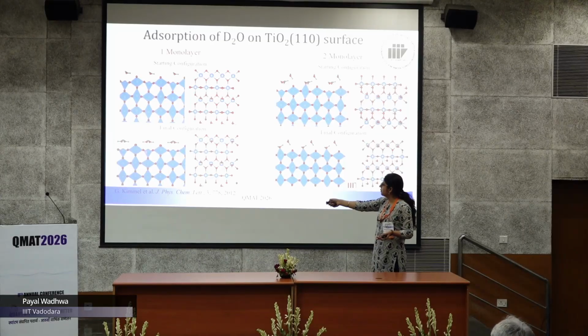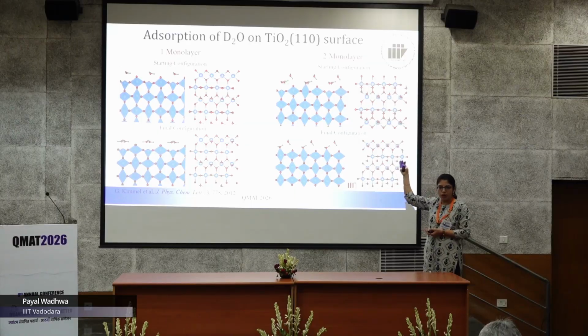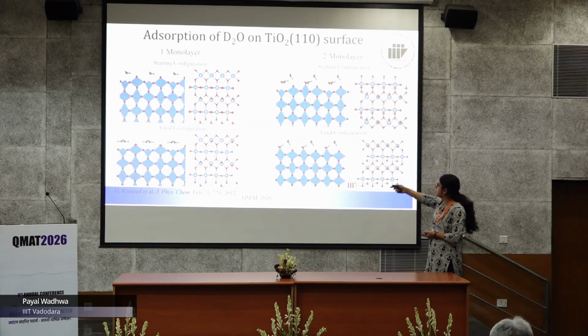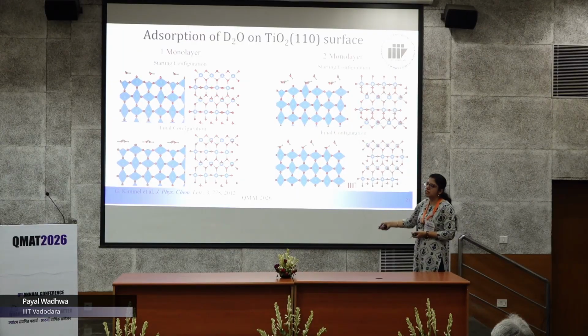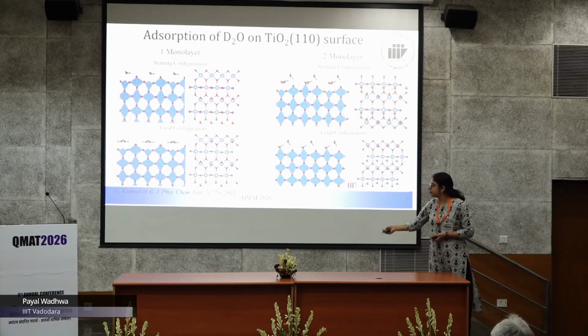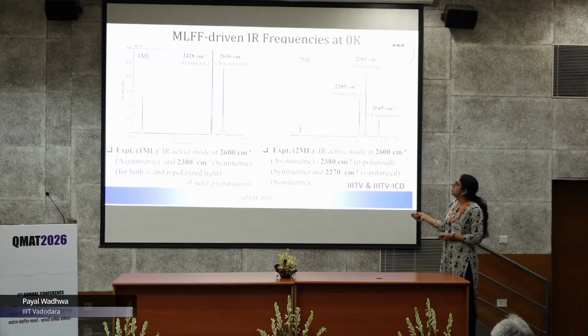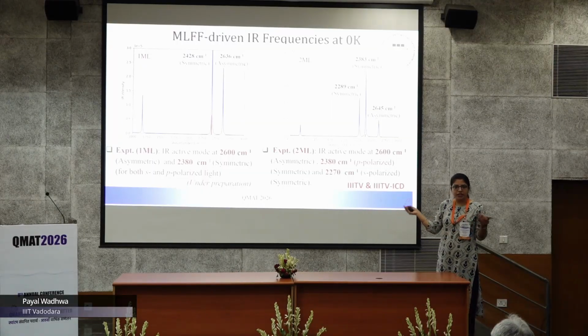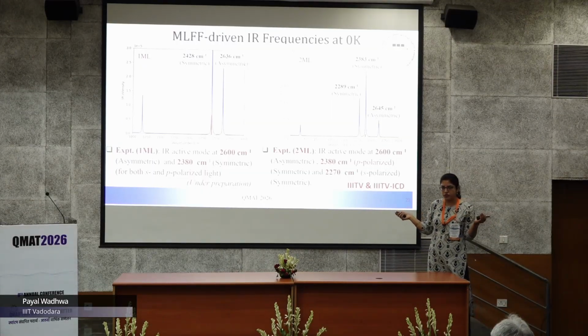We found that for one monolayer, it automatically follows the linear chain, and then we can also study the coverage dependence. We added 2 monolayers, and here we found a zigzag pattern, and this was in good agreement with the previous theoretical and experimental reports. We can also determine the IR frequencies, just generate the machine learned force fields.